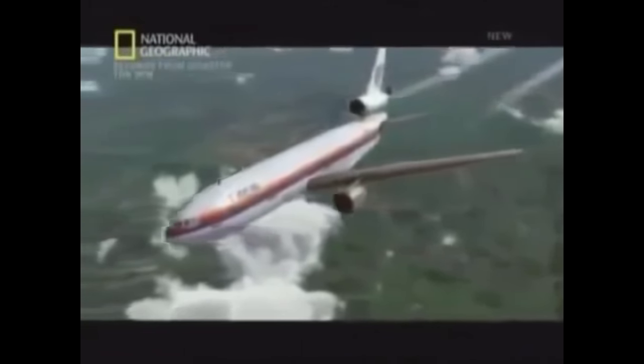The NTSB team can now put together the chain of events that left the passengers and crew of Flight UA-232 seconds from disaster. As the DC-10's fan disc rotates at 3,800 RPM, the huge stresses initiate a minute crack in the defect. With every flight, it grows fractionally bigger. July 19, 1989, 44 minutes from disaster. The fan disc has been in service for 15,503 flights over 17 years. The crack reaches 13 millimeters in length. The faulty fan disc can no longer cope with the stresses imposed by its rotation. It shears in two.